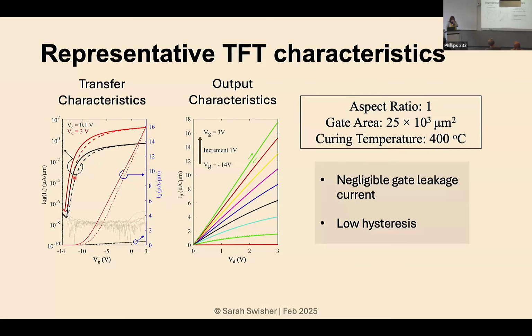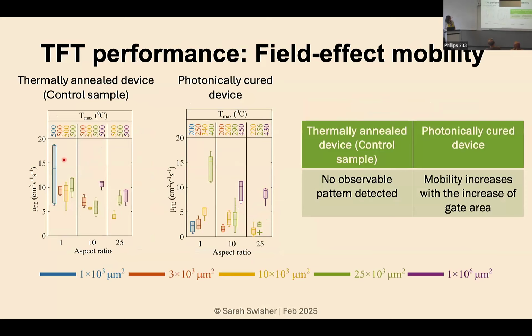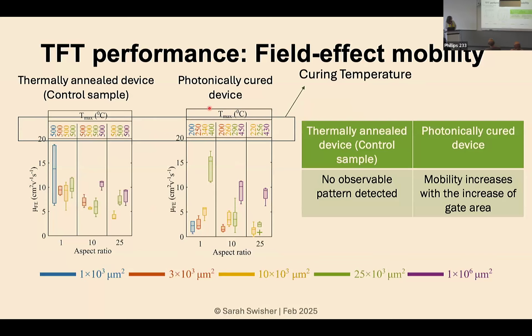So if we look at the control devices, these are our thermally annealed devices, all the different geometries, but they're all cured at 500 degrees. And these are our photonically cured devices. So you can see the temperature variation here. This is the peak temperature that was reached during curing. And what we're showing here is the field effect mobility of the transistors that we made with these 2 processes. And as you can see, for the control devices, there's some variation in the mobility, but there's no trend with area or with aspect ratio. So here the different colors are representing the different gate areas.